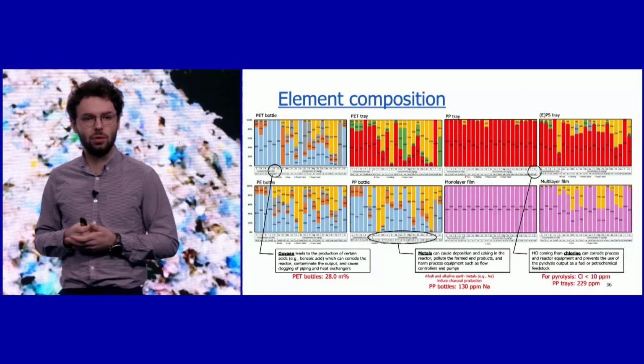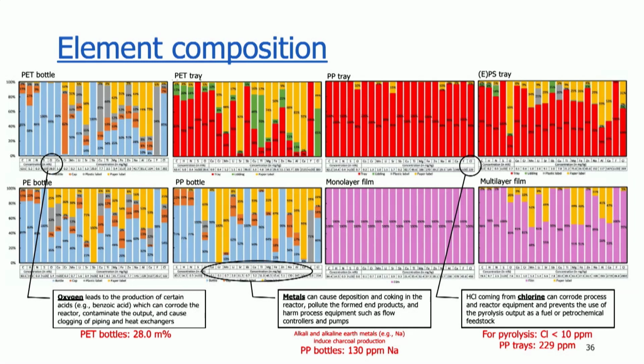When we take a look at the elemental composition, we see also very interesting results, but these are maybe a bit more relevant for thermochemical recycling. So what we see here is that there was a high difference in terms of oxygen content. For instance, the PET streams, or PET-based streams, contain a high oxygen content, and oxygen can, for pyrolysis of polyolefin-based waste streams, result in production of certain acids which can corrode the equipment.